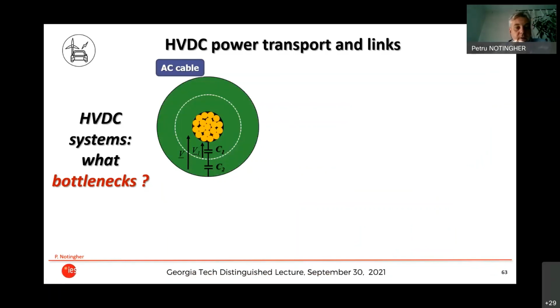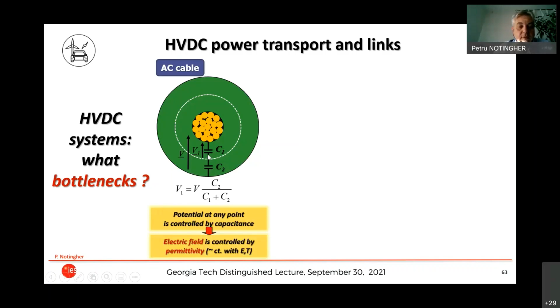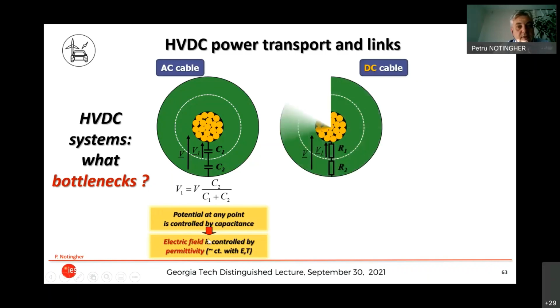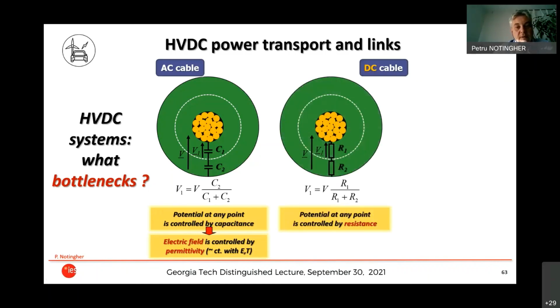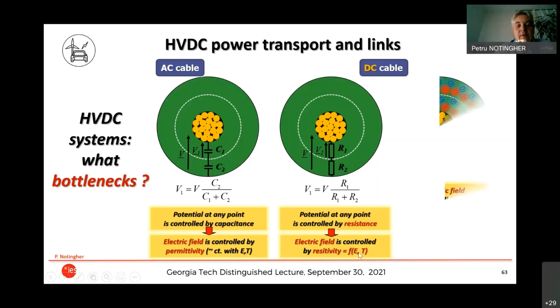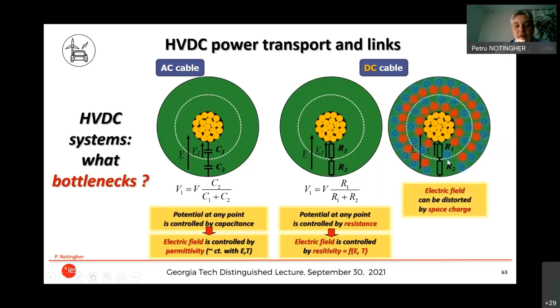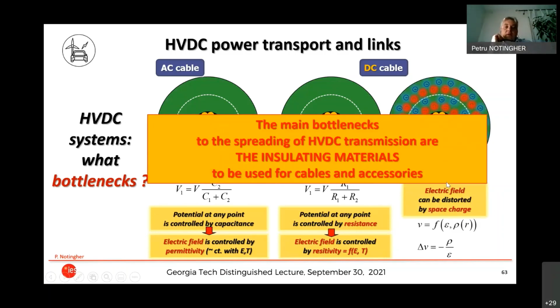And why does it happen? In an AC cable, you have a capacitive distribution because there is no resistance in AC. Now the resistance of the insulator doesn't count. It's only the capacitance. So the electric field is controlled by the permittivity, but in DC you will have the resistance and you won't have the capacitance. So the potential will be controlled by the resistivity, and the resistivity, as you saw before, varies a lot with the field and the temperature. And moreover, you will also have space charge, and this will distort the field even more. And this means that you will have to deal with this.